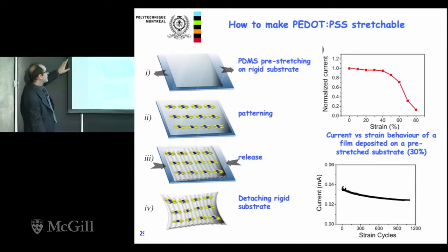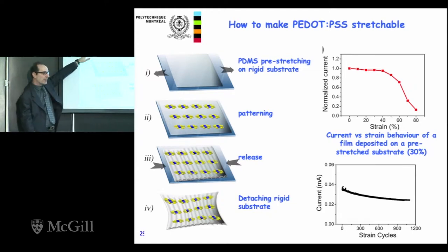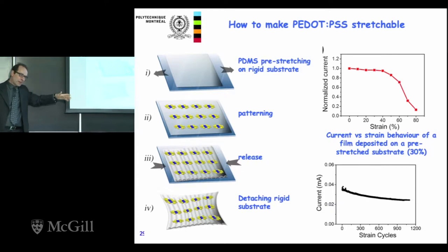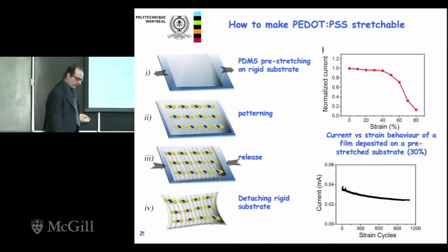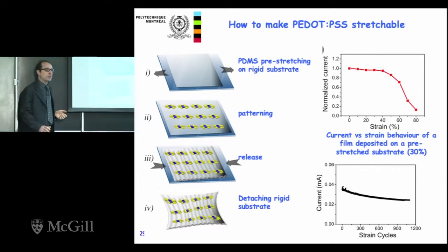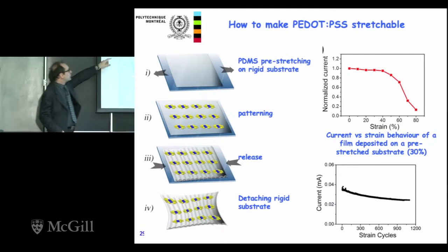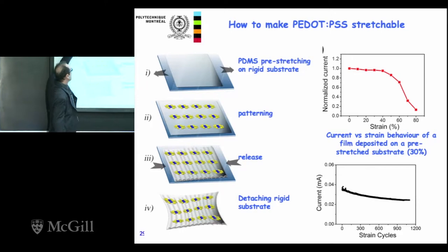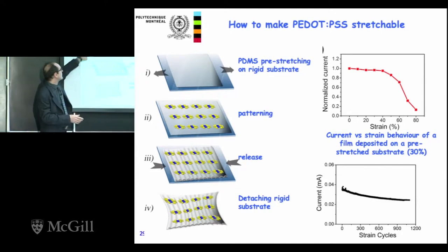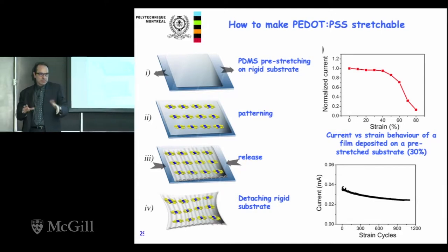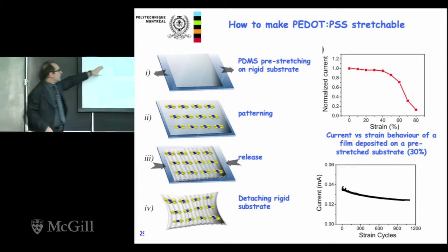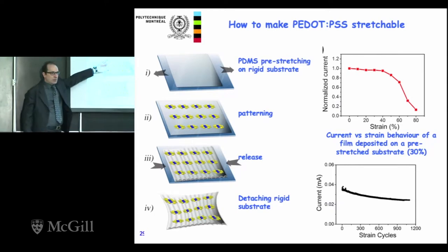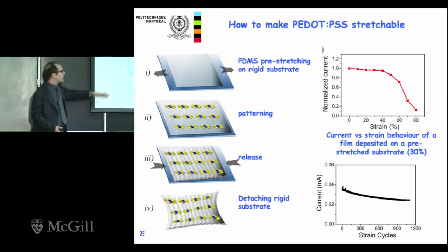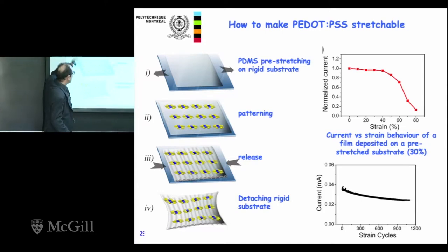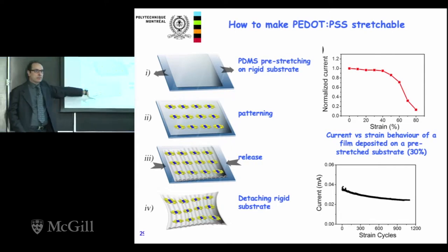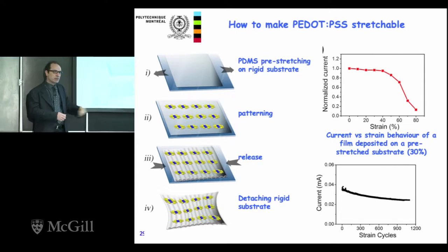But actually, the way we worked is that we use the so-called buckling technique, which was initially developed in George Whitesides' group at Harvard for metal electrodes. So what we do, we put our device under strain, our substrate, PDMS substrate under strain. This is quite a thin PDMS layer. It's about a few hundreds of microns. Then we carry out all our process while the device is under strain. So we carried out the metal patterning, polymer patterning, and at the end we release the device. So at the end we have a buckled substrate with devices on it.